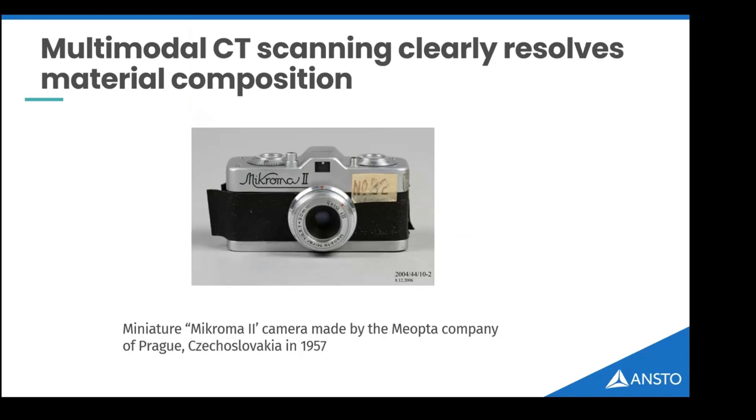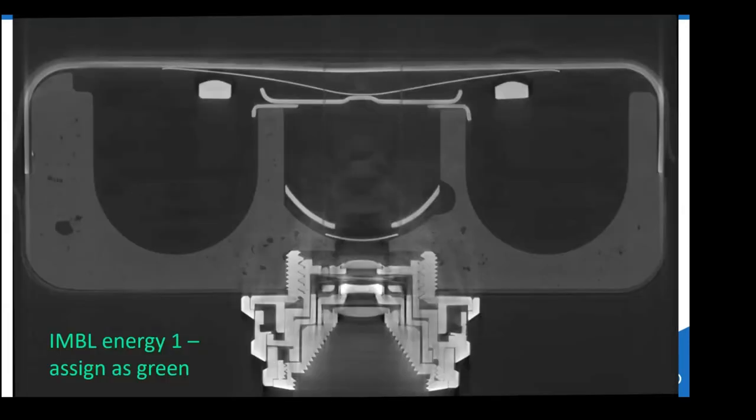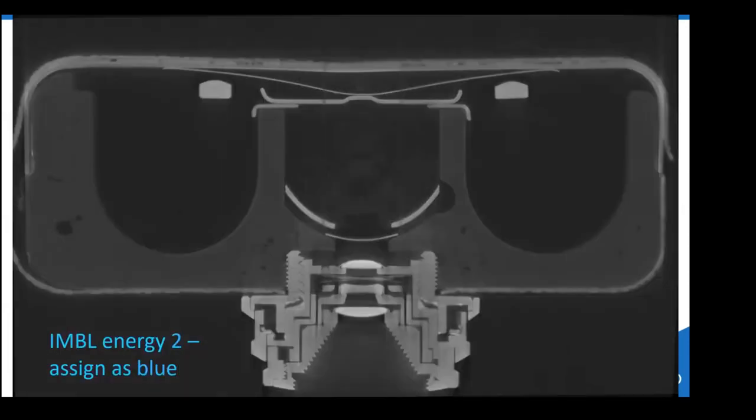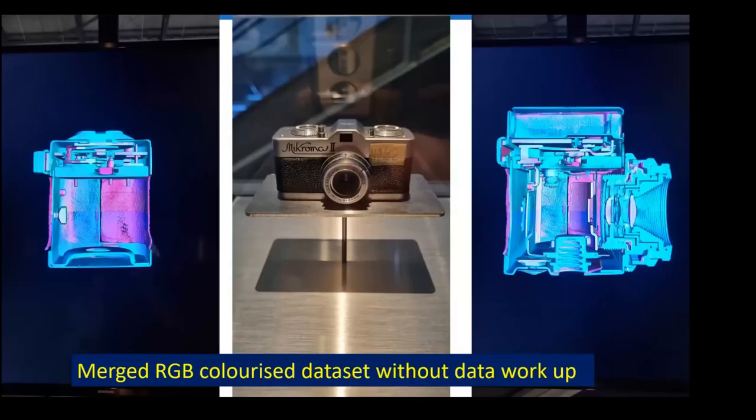This work has been reported publicly at the museum and also through the International Atomic Energy Agency and the United Nations. A final advance is combining neutron and X-ray scans: taking grey-value scans, looking at contrast using neutrons, monochromatic and polychromatic X-rays, and combining them to form a holistic image where we can identify materials within objects without opening them. This is a new method exhibited at the museum.